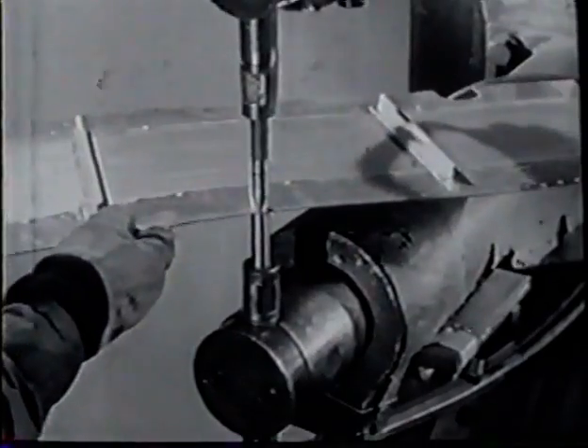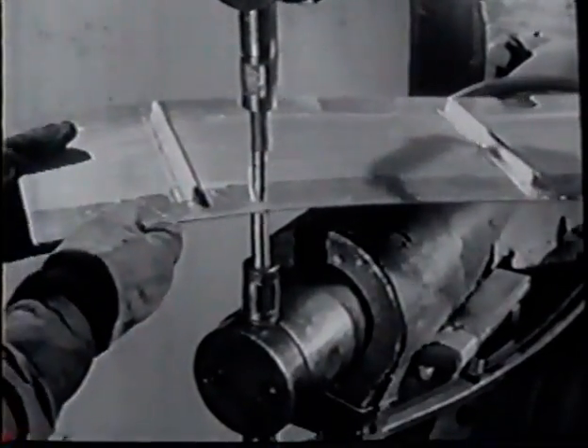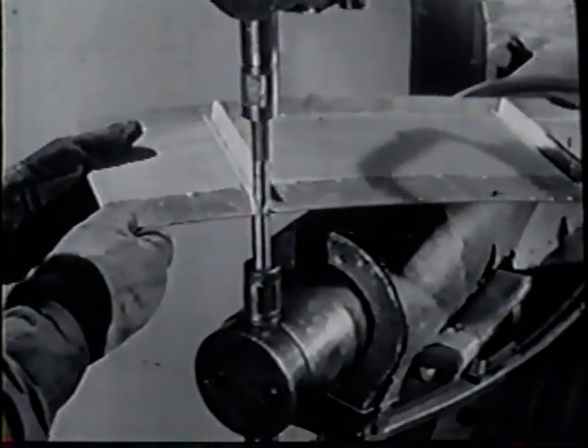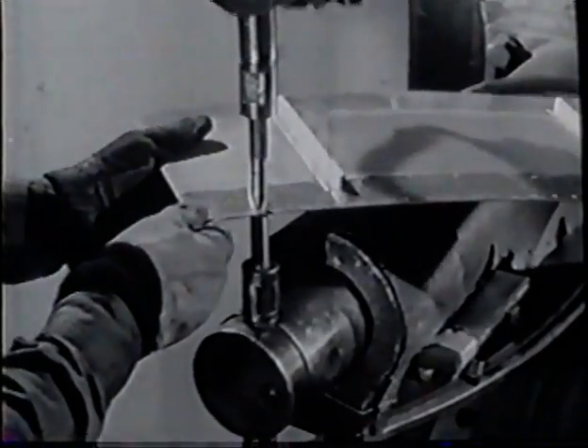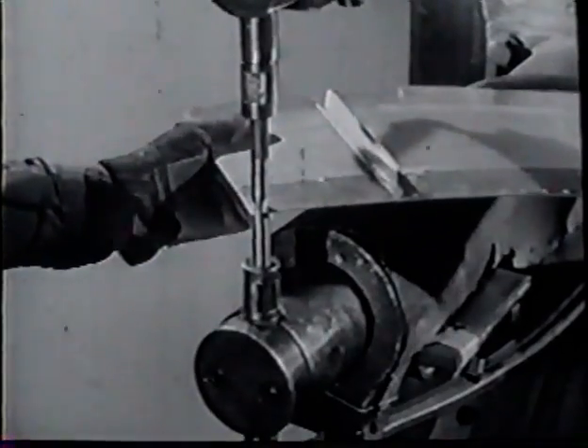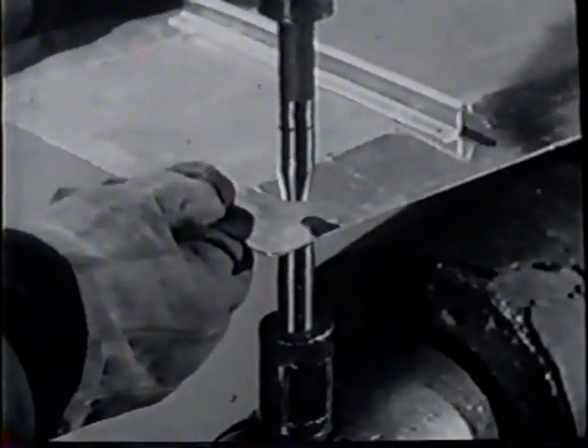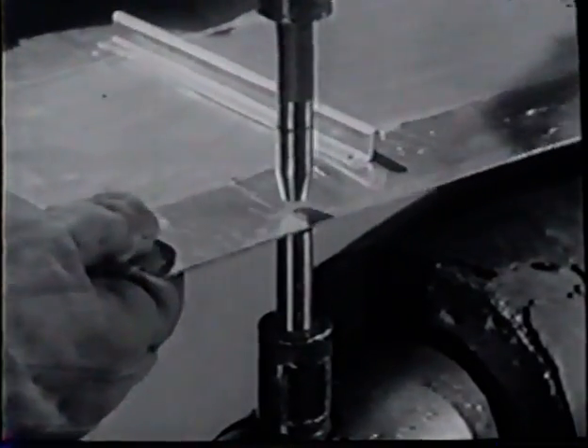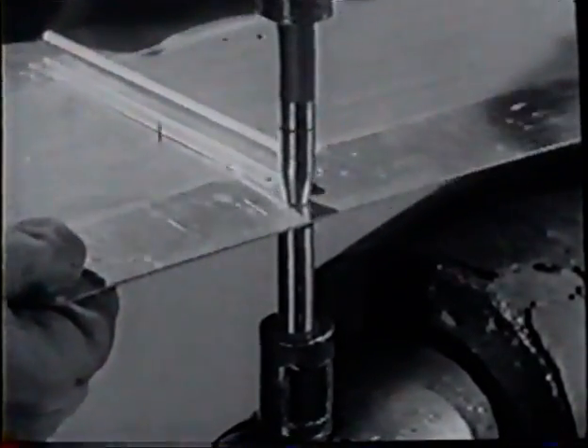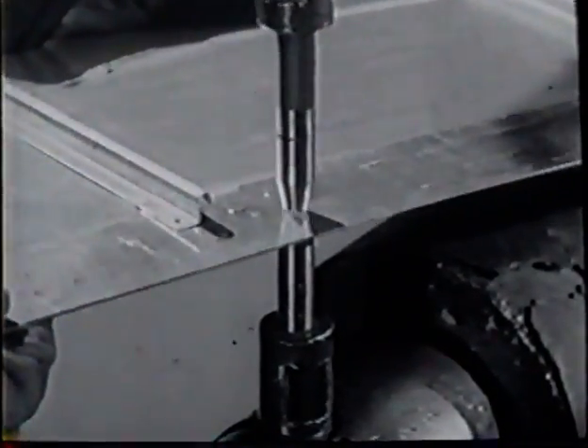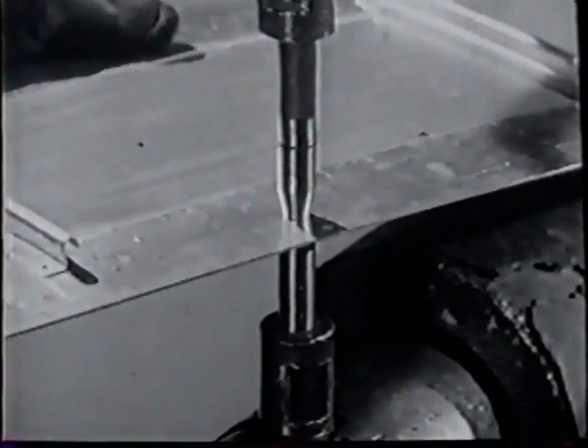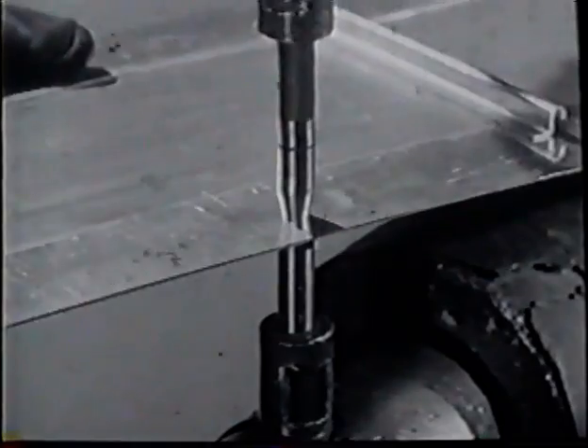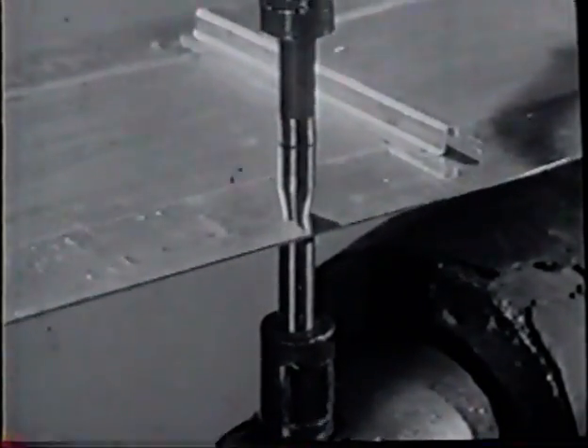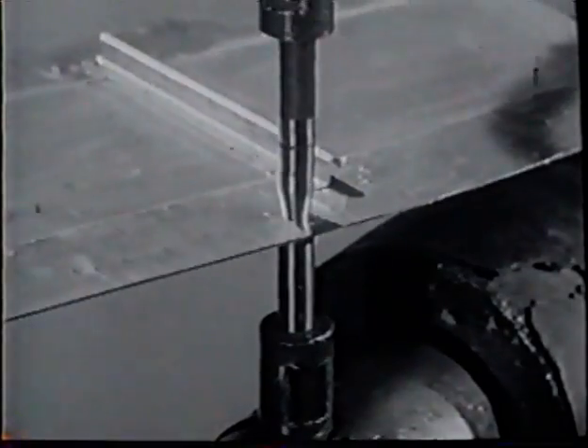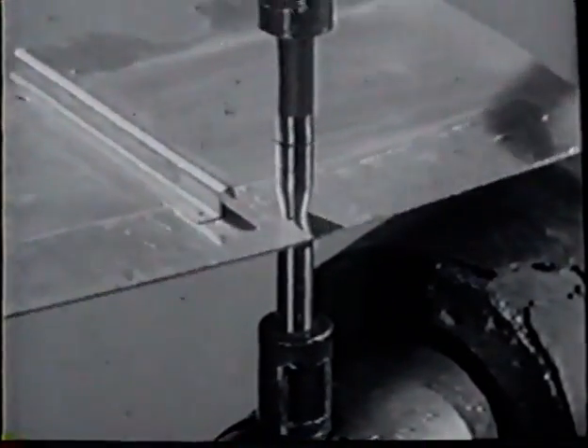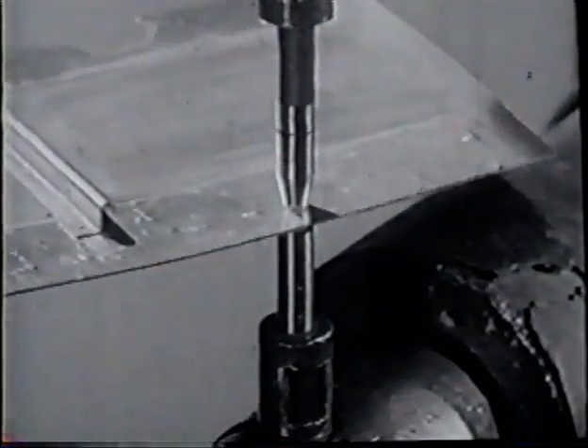Do not scrape it across the lower electrode. Don't weld too near the edge. Welds made too close to the edge are apt to be weak and result in cracking of the material or so-called spit-outs. Weld evenly. Keep the lines of your welds parallel.